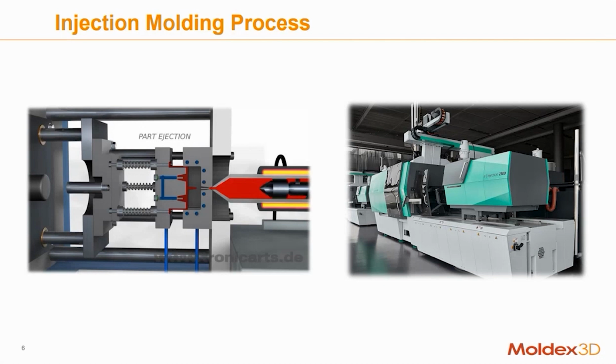During the packing phase, what's happening is the part is trying to shrink and warp on the mold surface, right? And the mold is acting as a constraint. It doesn't allow the part to shrink and warp. So what ends up happening is it will start building up stresses, right? If it's a semi-crystalline material, it will start to crystallize, right? So all those things happen simultaneously.